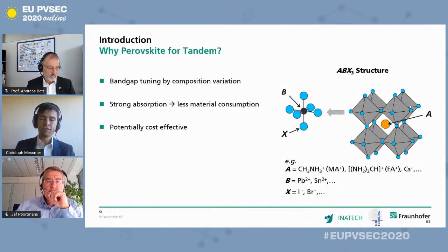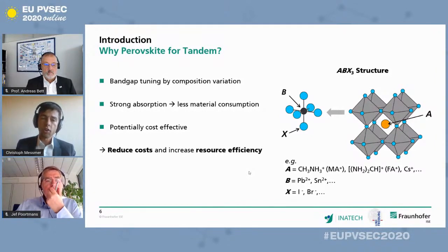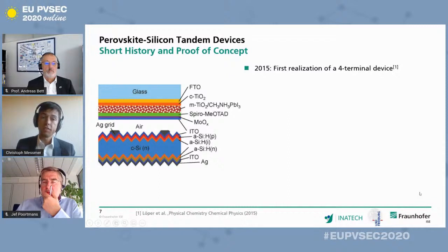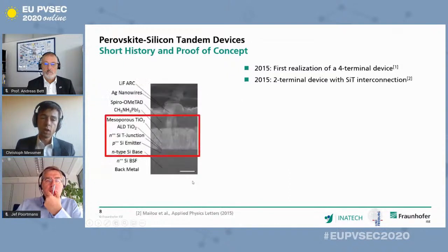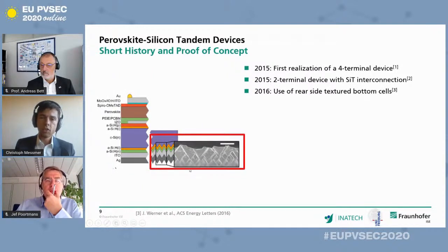But why are we using perovskite for silicon tandem solar cells? As you can see, the bandgap can be very nicely tuned by composition variation of the A, B, and X site. Also, this material has strong absorption, which leads to less material consumption, and also it's potentially cost effective. So it reduces costs and increases resource efficiency as motivated on the first slide. That perovskite silicon tandem devices have been very fruitful in the past, I'll show you by a short history of the research. In 2015, we had a first realization of a 4-terminal device, shown here. In the same year, we also had the first 2-terminal device with a silicon tunneling interconnection layer.